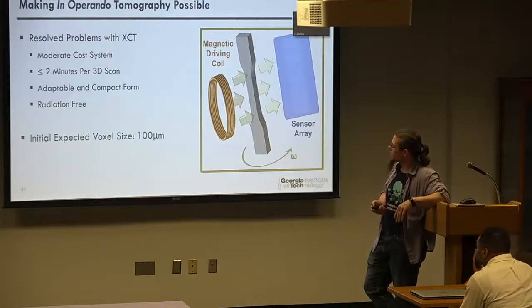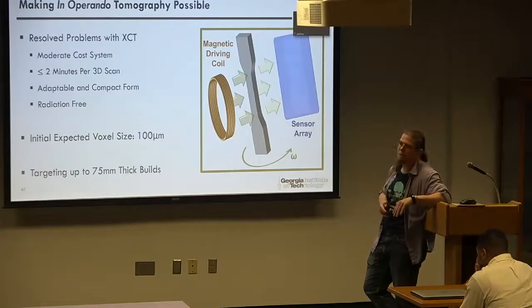The initial expected voxel size will be 100 microns, and then targeting up to 75 millimeter thick builds with this system.